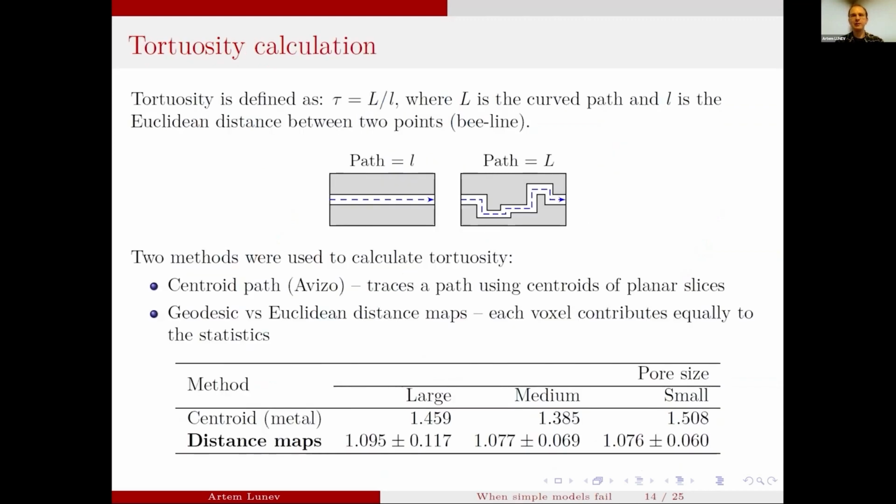So when we're dealing with porous materials, we have tortuosity, right? Porous materials are tortuous in the sense that the thermal wave, which starts to travel through the matrix, does not travel a straight path, but follows a complex curved path, which is greater than the straight line between 2 points.